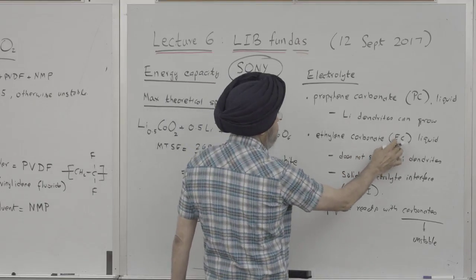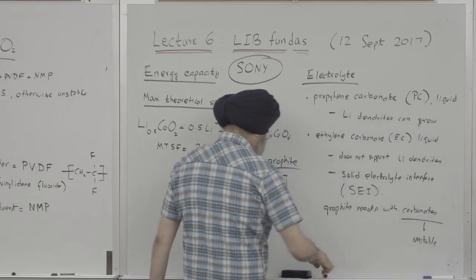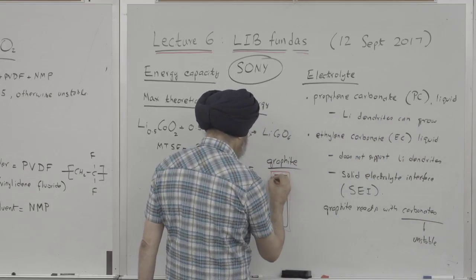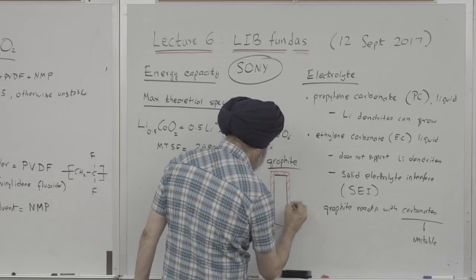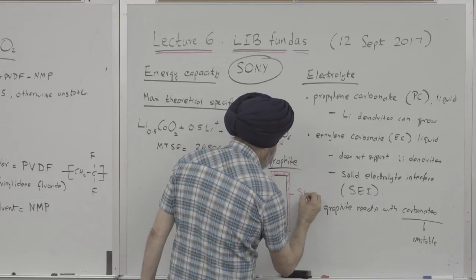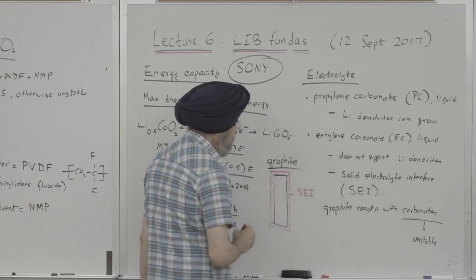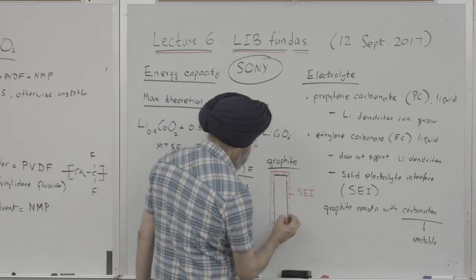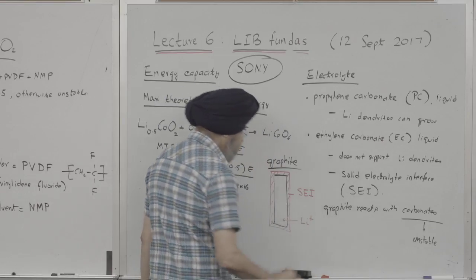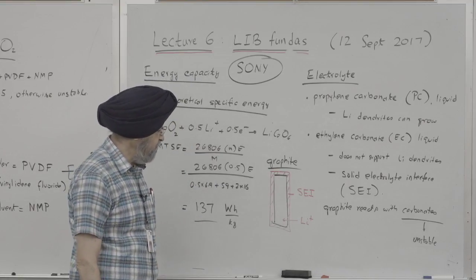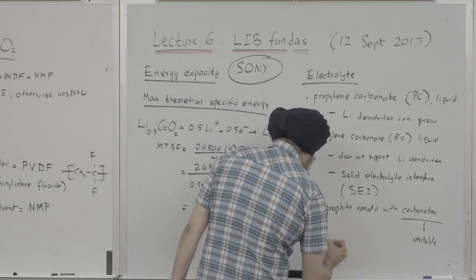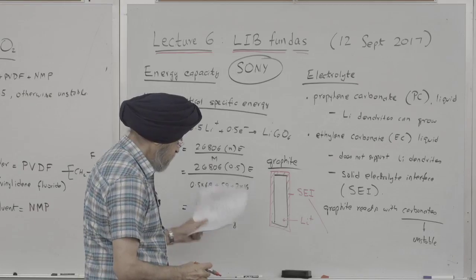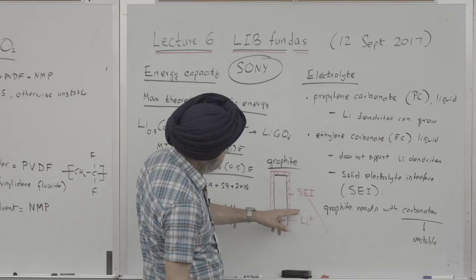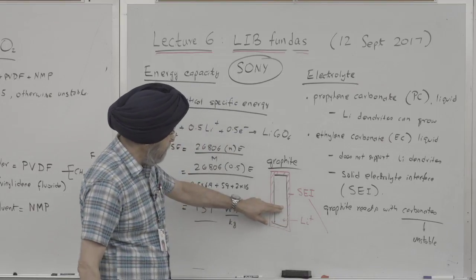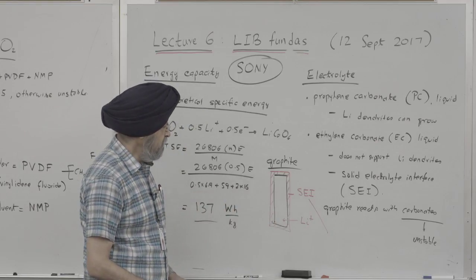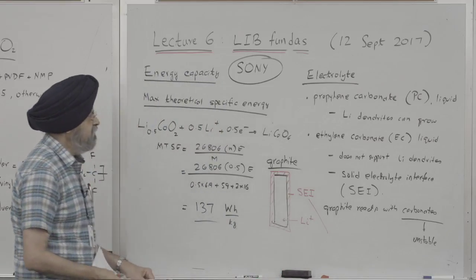But with this ethylene carbonate, there is a reaction that happens, and lo and behold, it forms a film on top of the graphite. And this is the solid electrolyte interface that forms. And amazingly, don't ask me how, the lithium ions can travel through this interface. Lithium ions have no issue going through it. So it keeps the electrolyte away from the graphite, but the lithium ions can travel through the solid electrolyte interface. I think this was a discovery made by Sony.